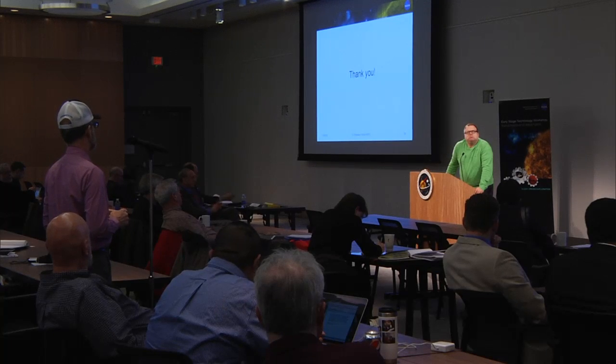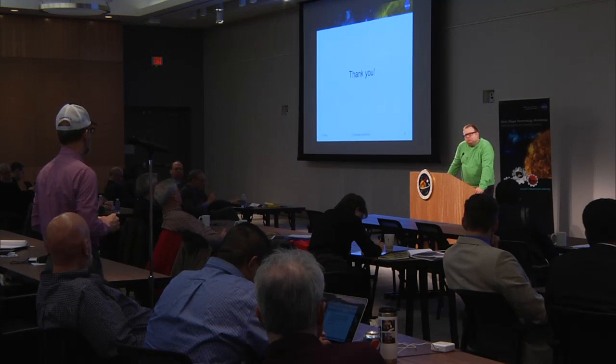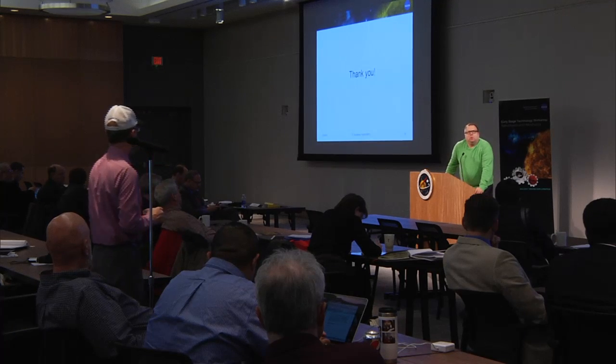Briefly, you mentioned microheaters. We use preheating substrates for vapor deposition. Is there some relationship there? Well, are you interested in measuring the stress for vapor deposition? To reduce the stress, if you preheat the substrate or pre-cool the substrate, then, yeah. In fact, we're looking at that now. This last month, we're exploring the capability to heat the substrate during deposition. Do you know what mechanisms you're planning on using? Electron beam? No, we use magnetron sputter deposition, but I use a thermal, radiantly heat the substrate from underneath. Filament. Yeah, filament, yeah.